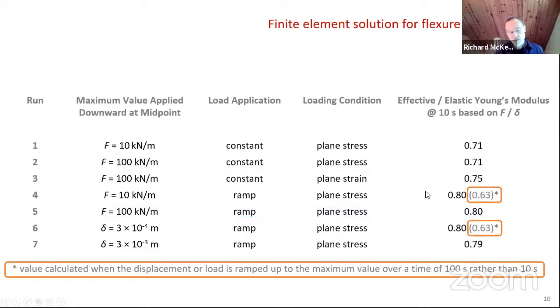I've also, you posed the question, okay, well, rather than applying a maximum value after 10 seconds, if I stretched out the time over which that load was applied to 100 seconds, you can see that the effective modulus based on total stress and total strain decreases quite significantly over that 100 seconds. If you spread it over 1,000 seconds, it'd be even less.